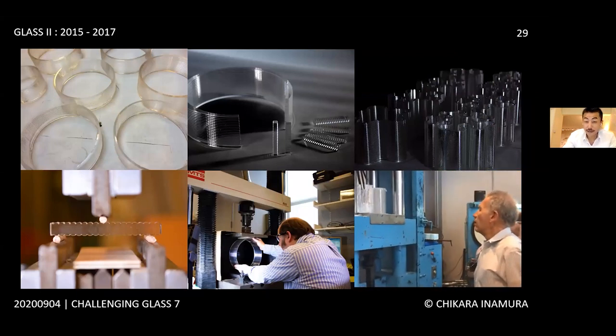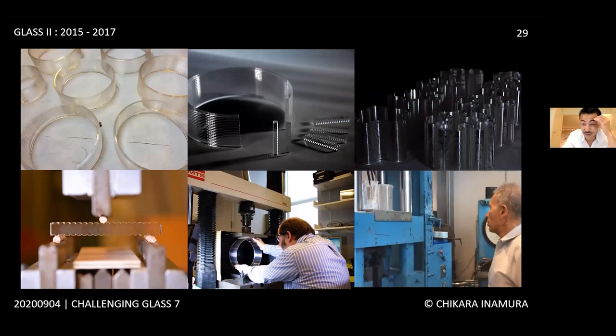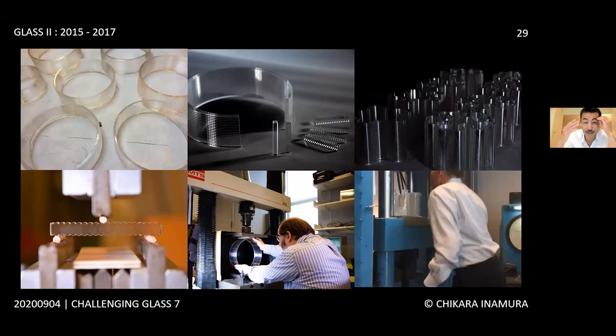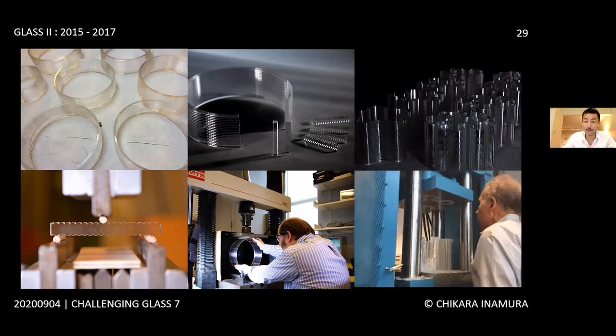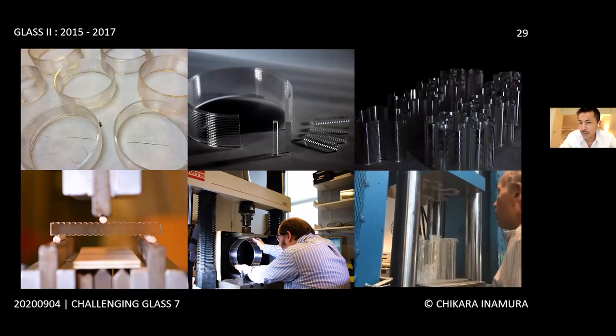Glass is also inherently inhomogeneous, and its effective strength for structural application is statistically determined based on large sample data. So we began collaborating with the Material Science and Engineering Laboratory at Simpson Gumpertz & Heger to conduct a series of mechanical and material characterizations of printed glass. When vertically loaded, the printed glass products carry up to 350,000 pounds in compression. Normalized to the cross-section area, this equals about 150 megapascals.